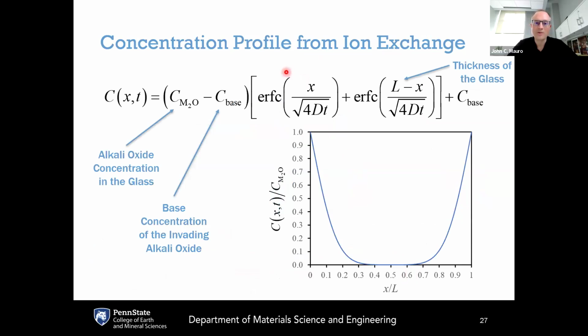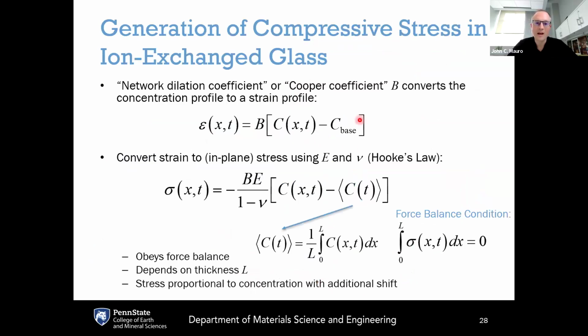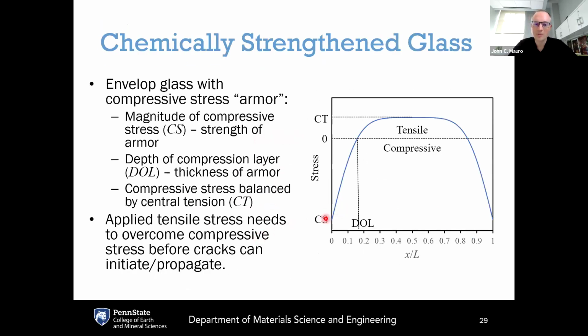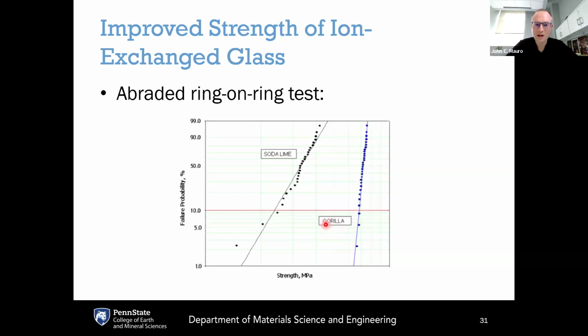thermal tempering. The stress profile follows this complementary error function, which basically follows the diffusion profile of the potassium. And this concentration profile here of the potassium gets converted into a strain profile by multiplying by this factor B, which is called the Cooper coefficient or the network dilation coefficient. This tells you how much strain that you get per mole percent of ions exchanged. And then that strain gets converted into a stress profile by multiplying by the Young's modulus over 1 minus the Poisson's ratio. And so you get a profile that looks kind of similar to the shape that we had with thermal tempering, except you tend to have a lower depth of layer and a higher compressive stress. So it gives you kind of more strength to your armor, but the armor isn't quite as thick compared to thermal tempering.